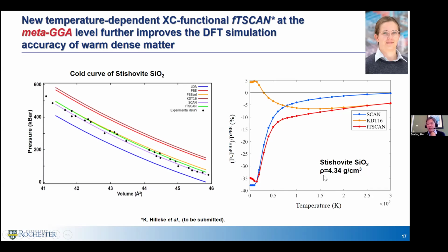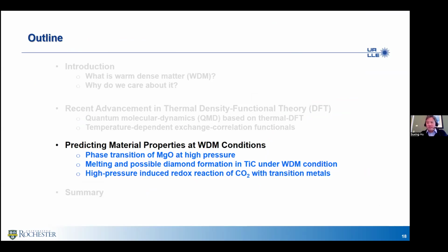And the right panel shows you if you apply a temperature to the system, right? Temperature here is from tens of thousands to hundreds of thousands Kelvin. And what you see is the difference between these predictions with the PBE. As you can see, this pressure difference can be as high as 30-40%, of course depending on the temperature range. So this gives us another example. Say, well, we are not wasting time developing something with no effect. So we are pretty happy. This effort does give us some confidence to better simulate warm dense matter.